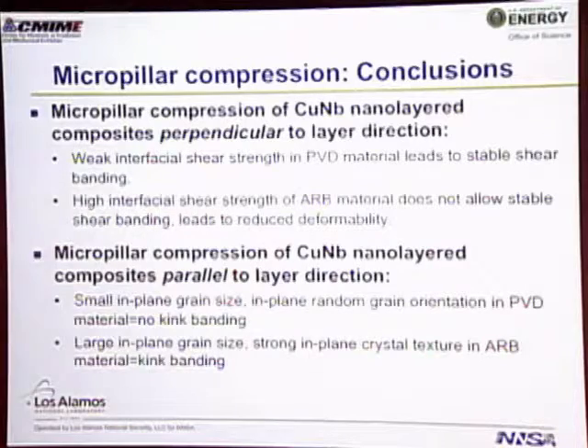So just to summarize here, what we find is that when we compress perpendicular to the layer direction, we see that the weak interfacial shear strength in the vapor deposited material gives us stable shear banding. If you change the interface to something that doesn't want to slide, you get very different fracture behavior. And when you look parallel to the layer direction, you can either get kink banding or no kink banding based on the types of microstructure that we have.